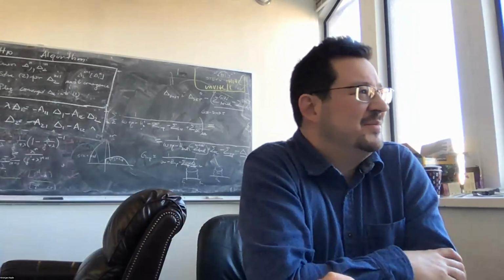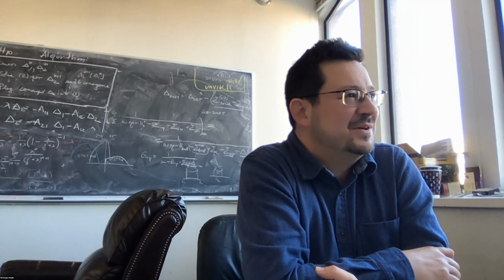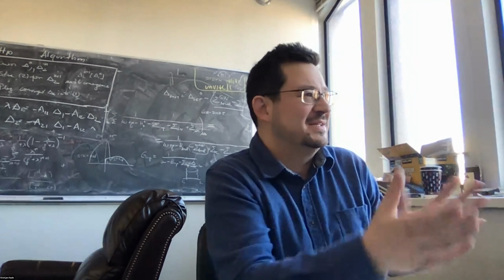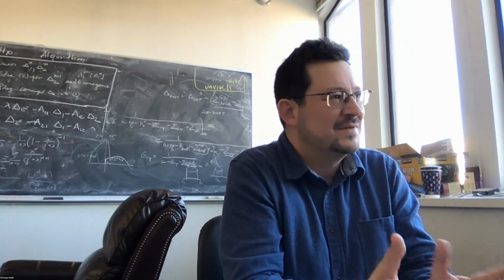If I may ask, the issue with the one-band Hubbard model, in some sense, is that when they do very precise calculations for the ground state, it seems that the ground state is almost always mostly wrong compared to cuprates. The cuprates physics is not in the ground state, it's in excited states. And of course, if you don't allow the ground state, which is usually stripy-like, then the physics is similar to the three-band model probably. But there's still something wrong with this Hubbard model, because you always have a stripy phase preferred. I know that this is hard to answer with the tools that you are using, but do you have any feeling of whether this issue that we have in the Hubbard model, that the stripes tend to be always preferred to the superconductivity, might be overcome when you have the three-band model? Is there any hope?